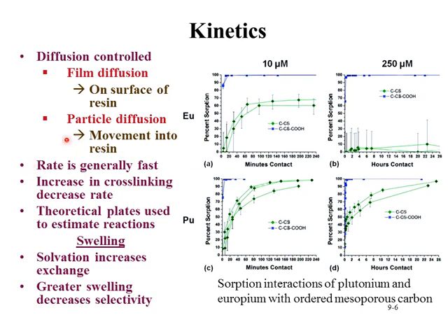Generally speaking, kinetics tend to be fast, or faster systems are preferred since separations are easier to achieve. Also, a general trend is that an increase in cross-linking tends to decrease the kinetics. In systems that are cross-linked, the exchange sites are often hard to access, so overall systems slow down.